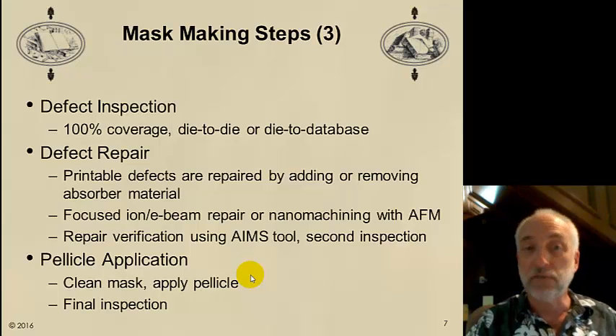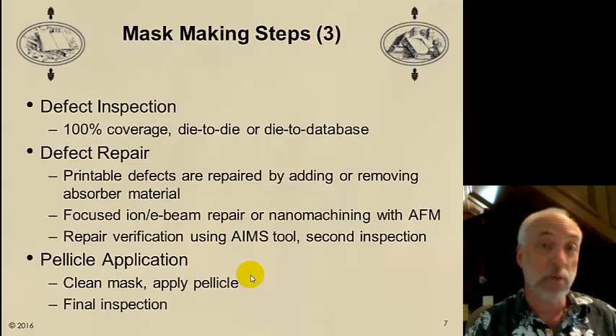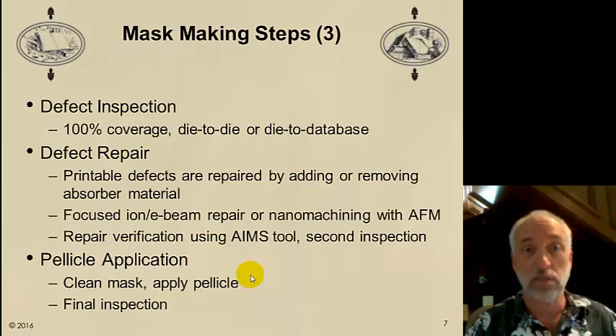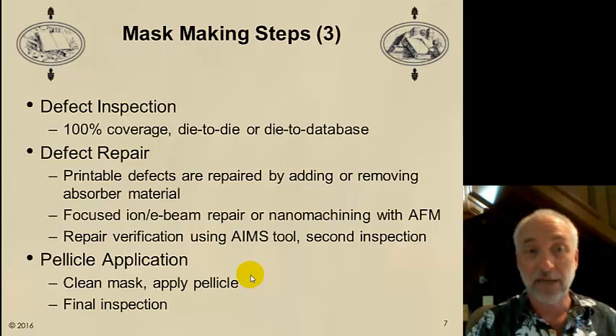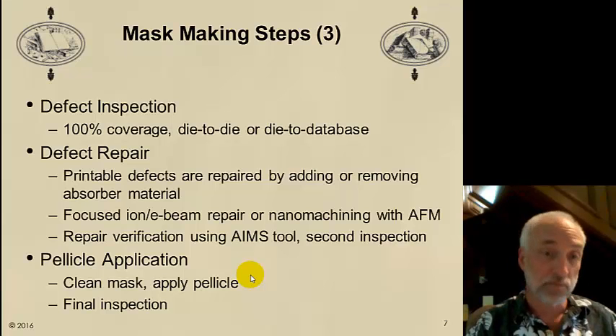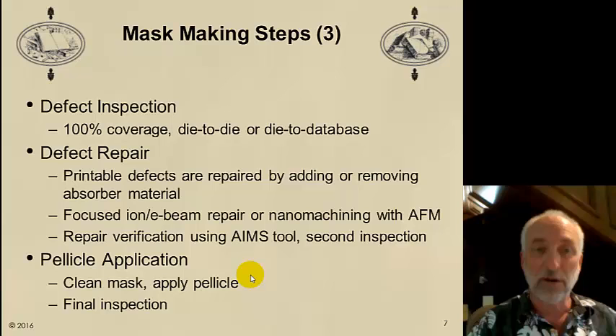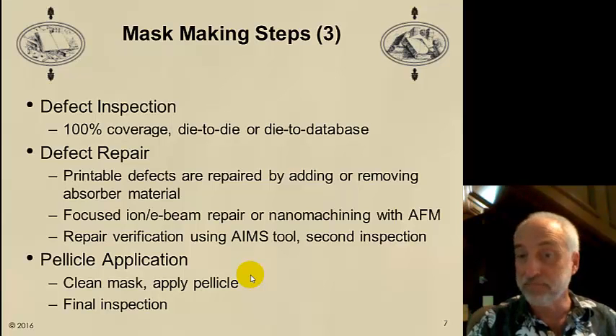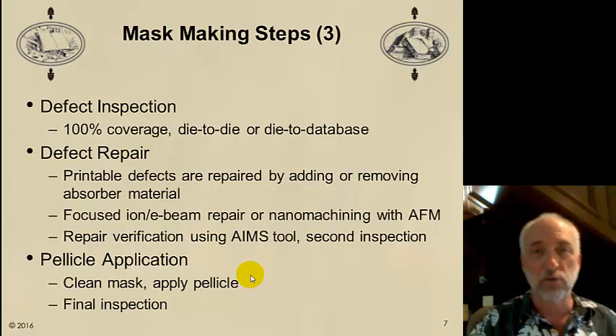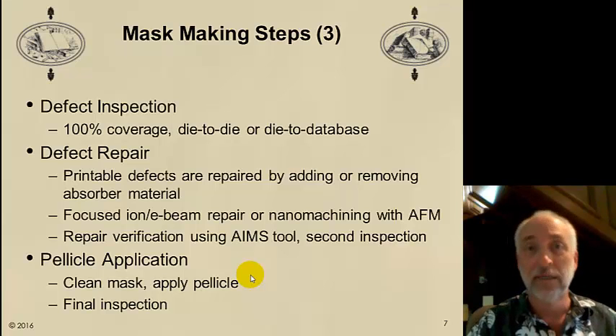If we find a defect in this inspection step, then we have to repair it. Well, we can throw the whole mask out and start over, but that's a very inefficient process because it can take a day or so just to write the exposure patterns on the mask. So it's much more effective, if we only have a few defects, to repair them. So we have specialized repair tools that can either add or remove absorber material as needed. We'll talk about these repair tools in a little bit more detail, not a lot of detail, but a little bit more detail in part 3 of this series on mask making.